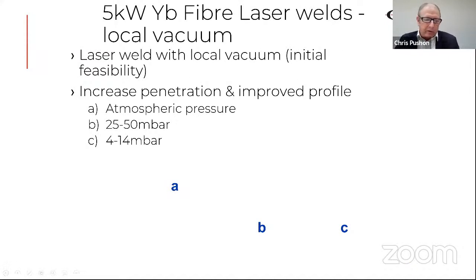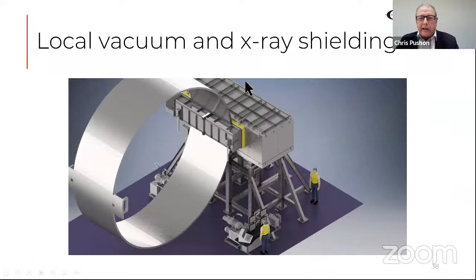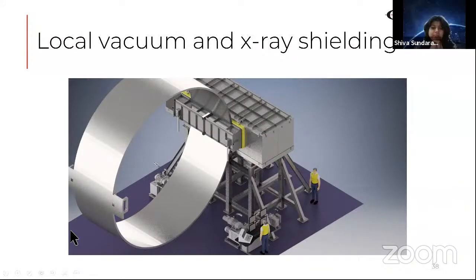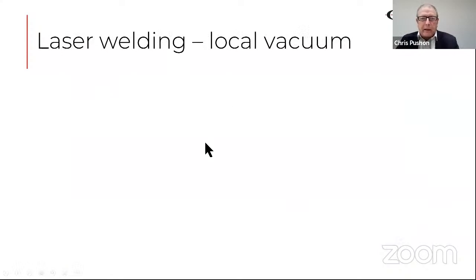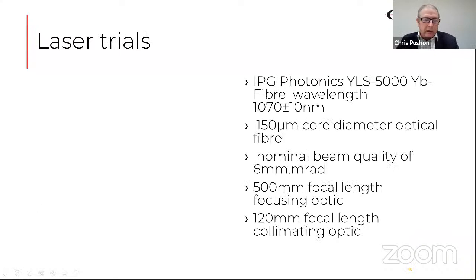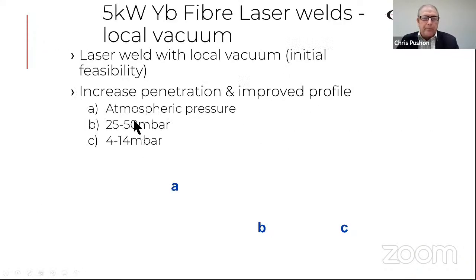I'll come back. So just to illustrate this, one of the other methods for eliminating the need for X-ray shielding is that instead of using an electron beam, we use a laser beam. And what you can't see in this picture is a local vacuum laser welding setup. I'll show you at the end, which allows you to weld both at atmospheric pressure, but also at a very coarse vacuum.